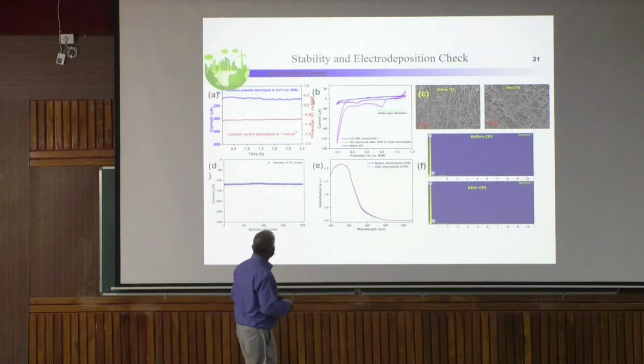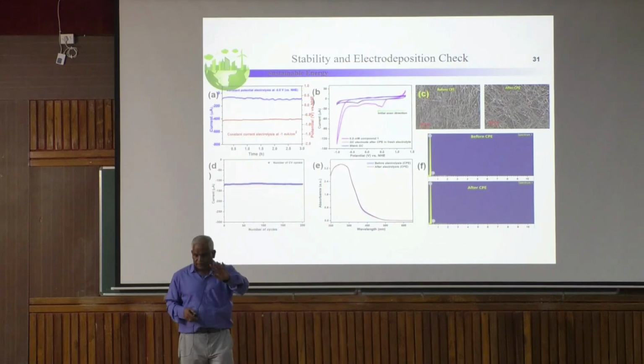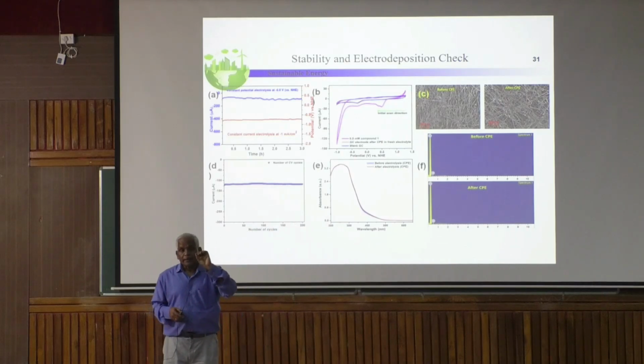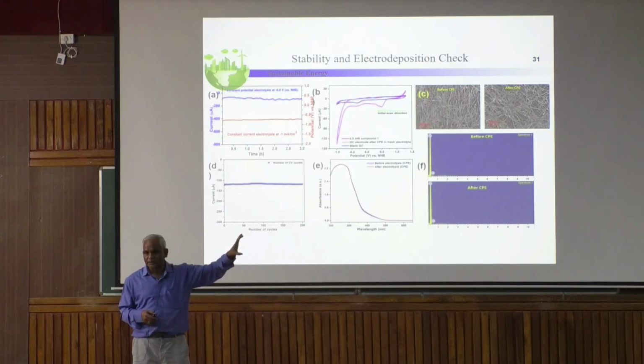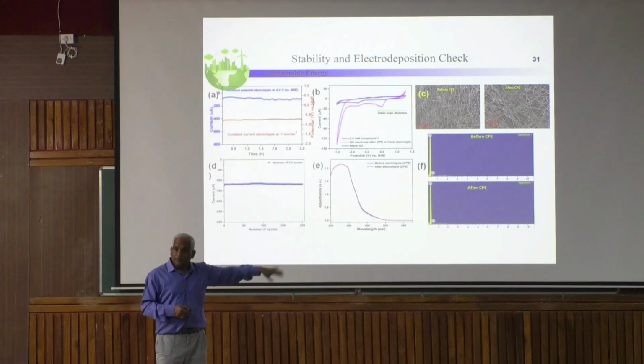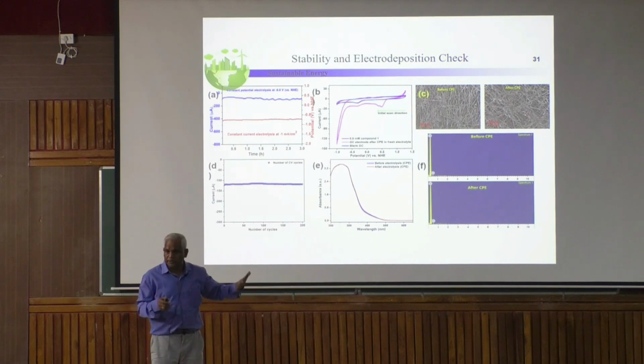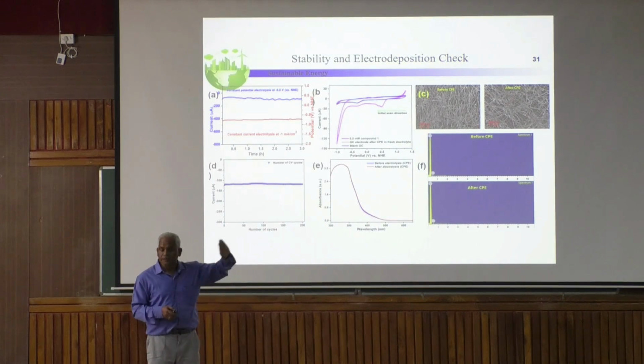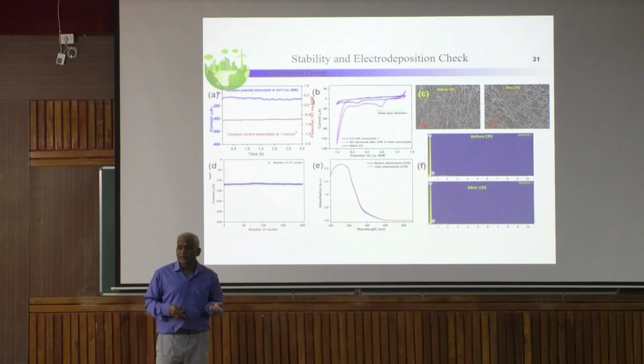Then, another thing I tell you, one trademark of any homogeneous electrocatalysis: you have to check and make sure there is no deposition happening. I told you many times, if you start with homogeneous, then after some time it gets deposited, and then finally that is the catalyst. For homogeneous electrocatalysis you have to do 100 cycles, 500 cycles, and again check the surface by microscopy. It will be the same. There is no deposition. So that we also did to prove it is homogeneous. Electrochemical homogeneous catalysis rarely happens; in the maximum number of cases it gets deposition.